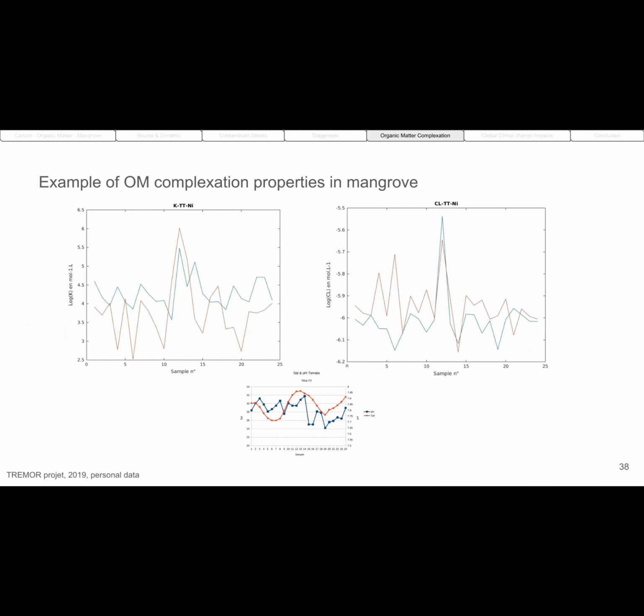Here are the results. On the left, you have the thermodynamic constant, which is the strength of complexation of this organic matter. In blue, it is the humic-like. No, it's not. We consider that there are two sites. In fact, we obtain this. There are two sites of complexation on the organic matter, one in blue and one in red, and it corresponds to two pools of fluorescent organic matter that react with metals.